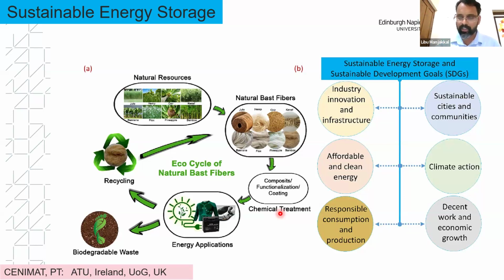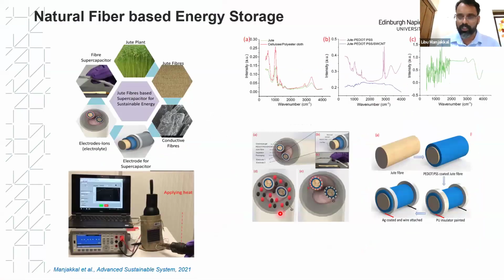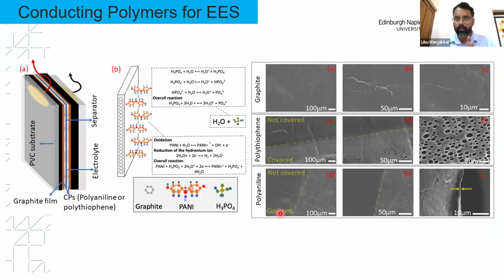Some of the papers are now under review in this area, where we got pretty good results on that application. As I mentioned, I'm describing one small work we recently published on a conductive polymer. We have a PVC or graphene based PVC substrate on which a graphite film was coated by spin coating. Here you can see the graphite covered with polythiophene, and we also used another conductive polymer, polyaniline, because we need to compare which conductive polymers show better performance in sustainable electrode fabrication for an electrochemical energy storage device.